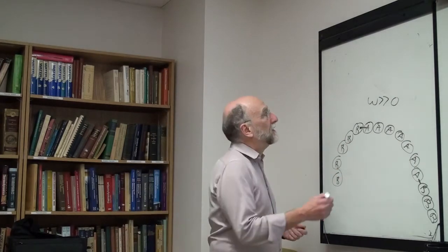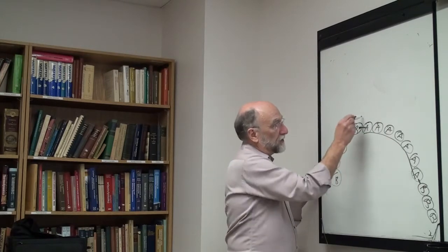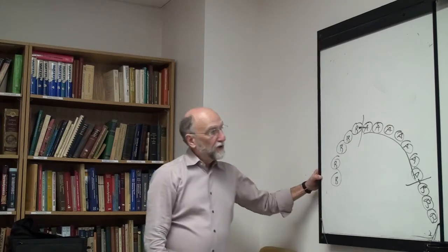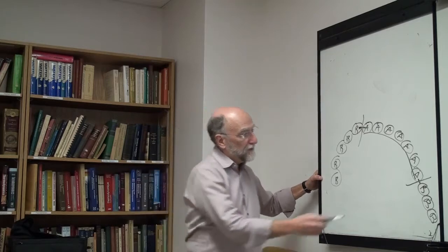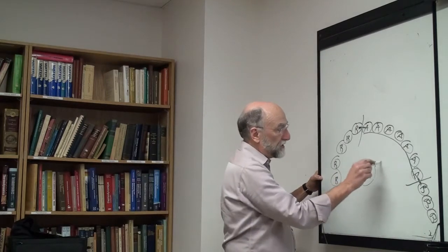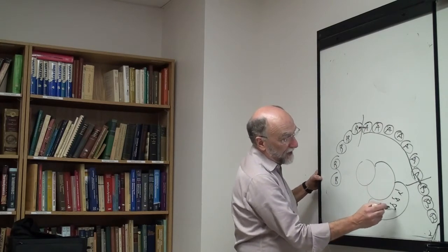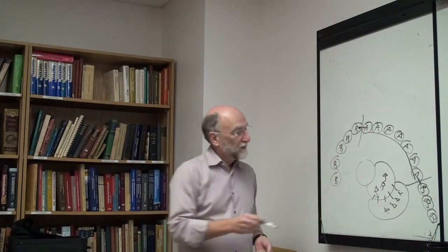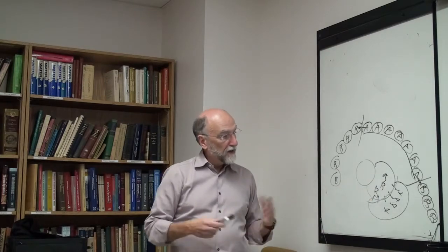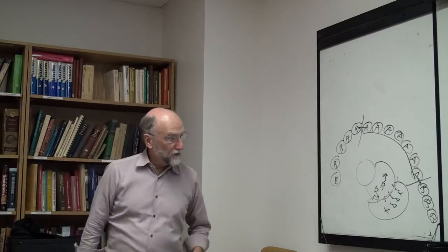Why, physically? It would seem to me that in 1 dimension, these are your groups, and your groups are only joined by AB bonds at the ends. So the number of AB bonds is extremely small, whereas in 2 and 3 dimensions you can end up with domains. These domains are rich in A, these domains are rich in B, and there's a lot of AB bonds between the 3-dimensional domains. So the number of AB bonds can remain higher. This is not totally satisfying to me either, but I think it has something to do with that.